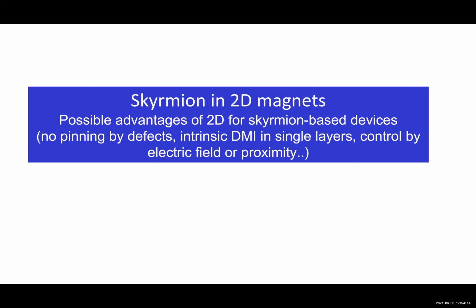And also, one of the difficulties with usual skyrmions is what is called the skyrmion Hall effect. That is, the motion is not in the direction of the current, but is somewhat oblique with respect to the direction of the current. And so this is something that must be solved. One of the attempts to solve this problem of the deflection of the skyrmions is to work with anti-ferromagnetic skyrmions, synthetic anti-ferromagnetic skyrmions, that is, to couple two magnetic layers and two skyrmions in two different layers by an anti-ferromagnetic coupling, and then the motion of the skyrmion becomes longitudinal. And we see that the 2D magnets maybe allow us to solve this type of problem.